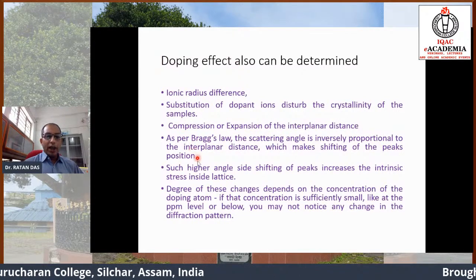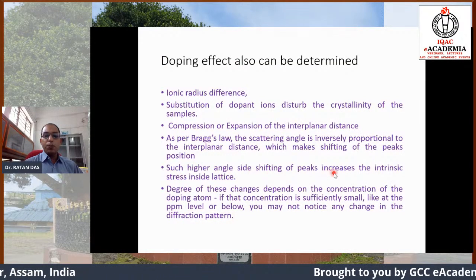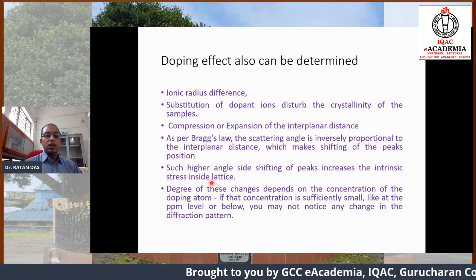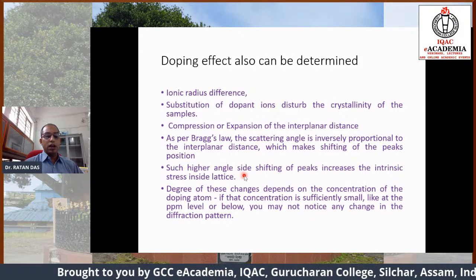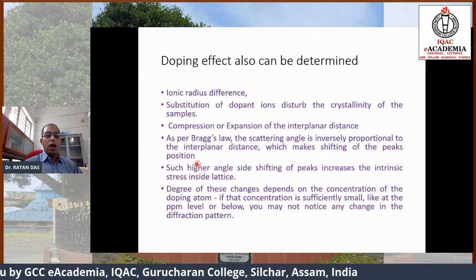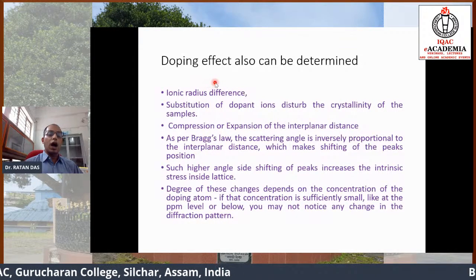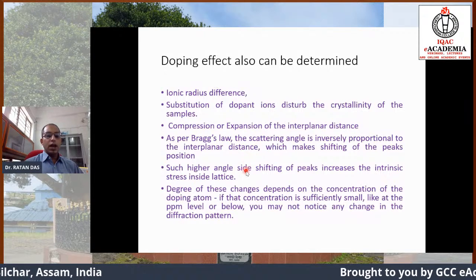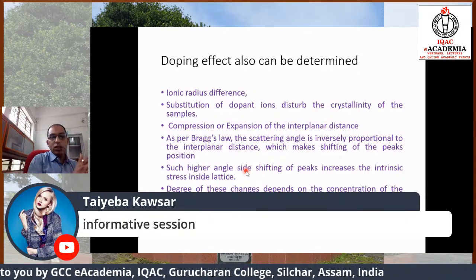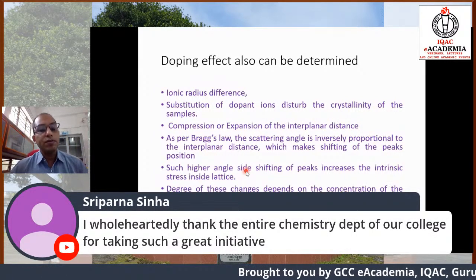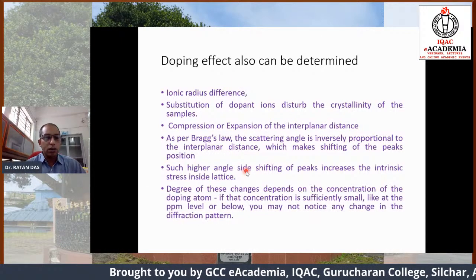So the higher angle side shifting of the peak increases with intrinsic stress inside the sample. Why am I saying the higher angle side? If the ionic radius is higher than the host material, then expansion will take place. And in the case of expansion, suppose at a particular 30-degree angle we are obtaining the 2 theta value, at the lower angle side we may obtain it. But if compression is taking place, then the higher angle side shifting will take place.